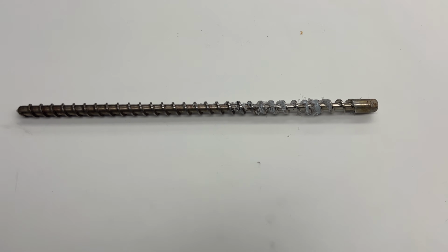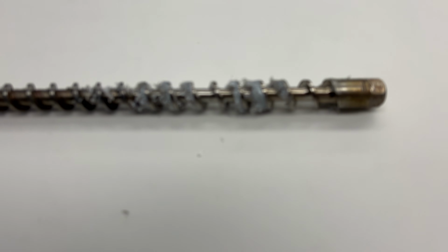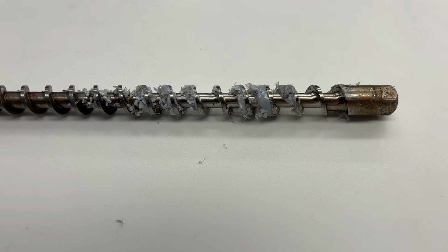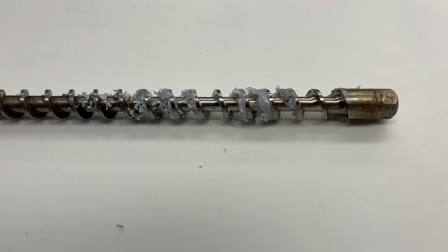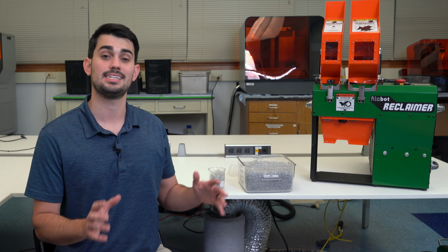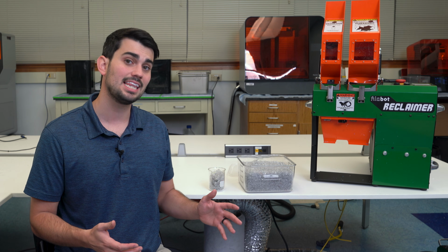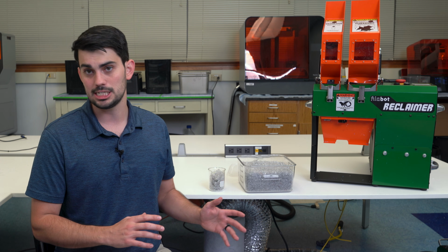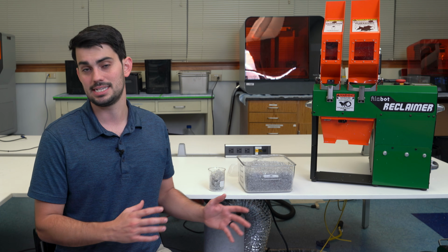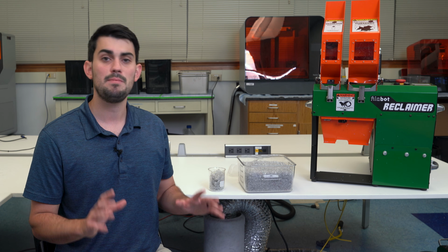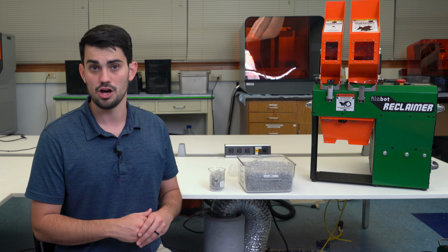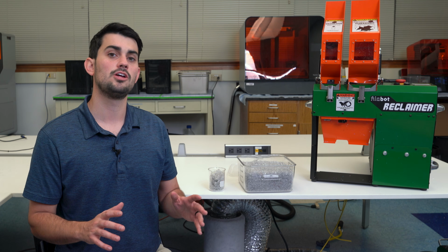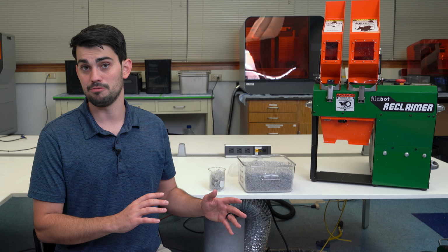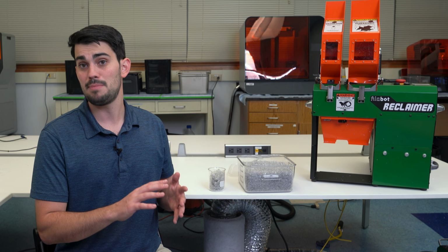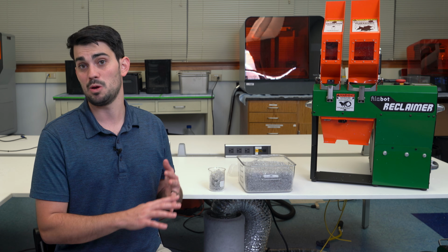One thing I learned during testing was that too high of screw speeds can cause premature melting, which increases the potential for plugging in the feed section. I'm going to take the extrusion process nice and slow and expect a highly irregular output. Even if I can't spool it, I will collect the strands and pelletize them. Once I get it to a pellet, many of those aforementioned problems will be resolved during the second round of extrusion. Take a look at this montage of processing the bottle flake to a 3mm filament, pelletizing it, and then re-extruding it to a 100% recycled spool of filament.